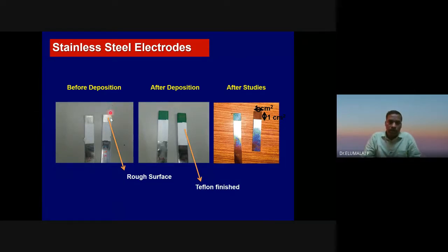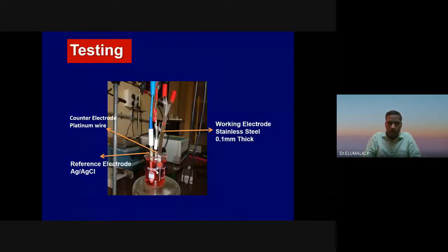So this is your substrate. Then I don't know how many of you can recognize what material it is. It is nickel hydroxide. You believe it or not? Nickel hydroxide. How will you deposit nickel hydroxide? We need to have some nickel source, a nickel 2+ source. So I take maybe nickel nitrate in the bath. Here, this is cobalt anyway. If it is nickel, it would be green.